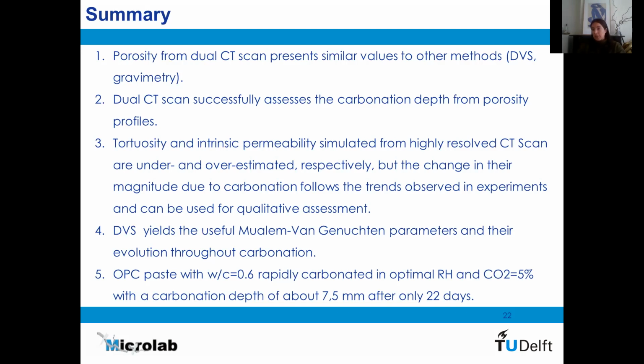And regarding the material that we use in this study, the Portland cement paste with a water cement ratio of 0.6 carbonated very rapidly at an optimal relative humidity of 65% and a concentration of CO2 of 5%, with a final carbonation depth after 22 days of 7.5 millimeters.